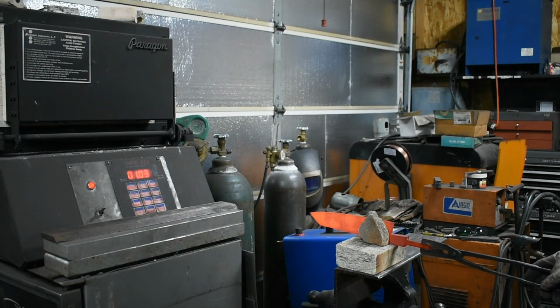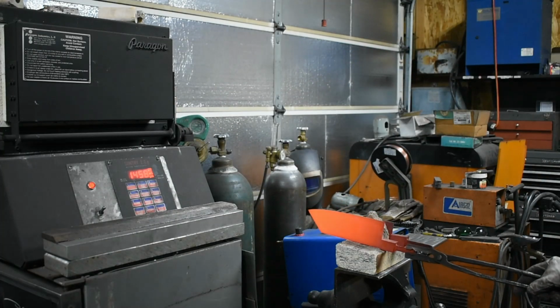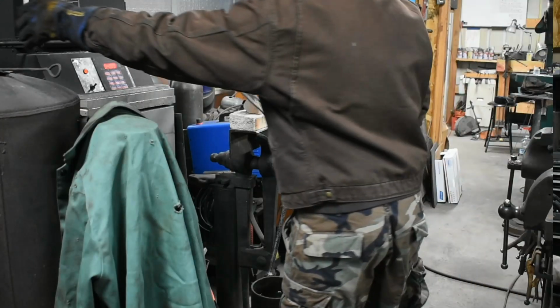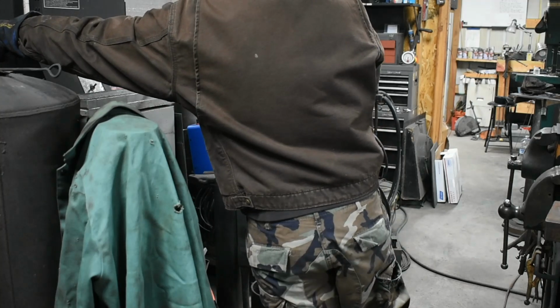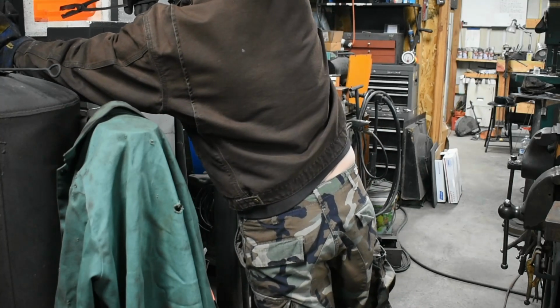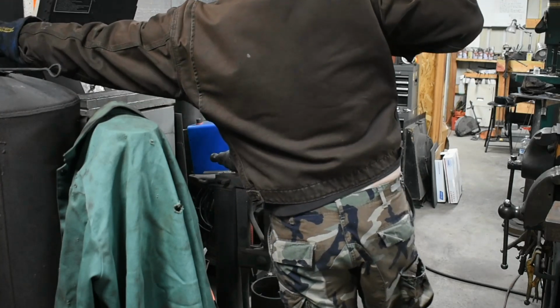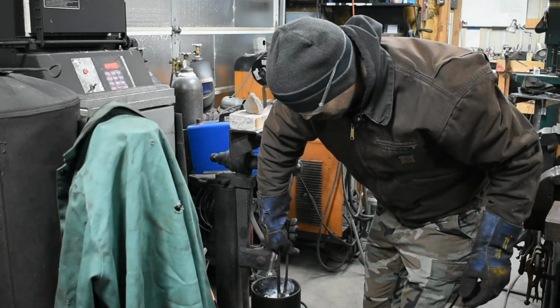Just lovely. Right now I'm normalizing these. So I brought them up to temp, soaked them for a minute, and now I'm just going to air cool them down to 700-800 degrees just to set them up for the quench and remove any residual grind warp or grind stress. And here we're quenching.